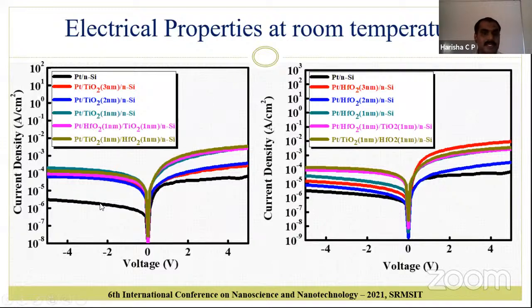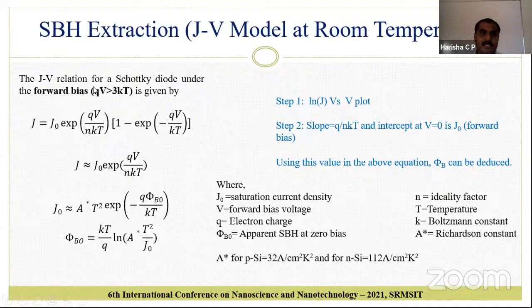we have observed that there is an increase in reverse current. The reverse current improvement shows that there is a reduction in the Schottky barrier. At the same time, there is a slight increase in the forward current also. This may be because of the lower band energy of the inserted dielectric, which reduces the series resistance. With hafnium oxide also, we have seen the improvement in the reverse current. This clearly shows the reduction in Schottky barrier height. For the extraction of Schottky barrier height, we have used a JV model at room temperature, which considers forward bias. But considering forward bias will not fetch you an accurate result, because it will not take the Richardson constant into consideration.